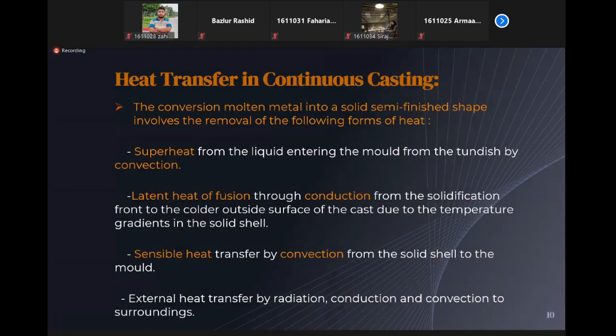So heat transfer is a major phenomenon when it comes to continuous casting machines. The distance from the meniscus, where the solidification starts, to the cutoff strand should be greater than the metallurgical length, which depends on the rate of heat conduction through the solid shell and the heat extraction from the outer surface, to avoid any cutting into the liquid core. So the casting speed has to be limited to allow sufficient time for the heat of solidification to be extracted from the strand, so that the strand is fully solidified.